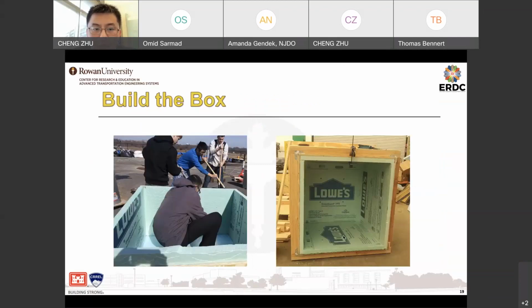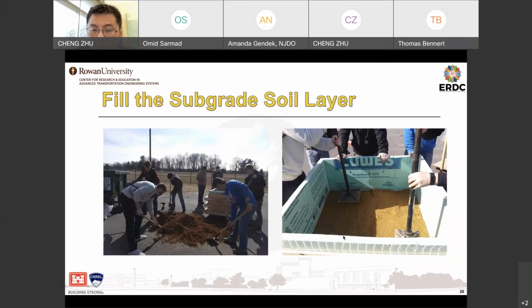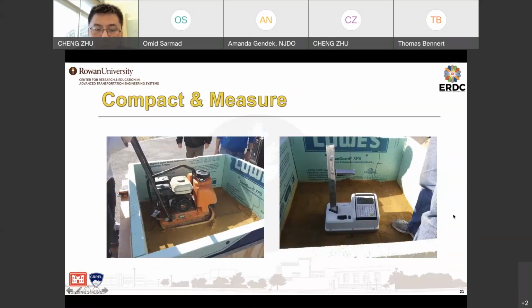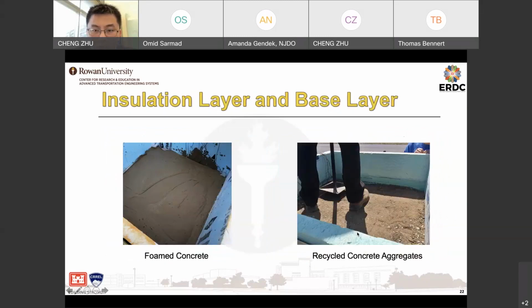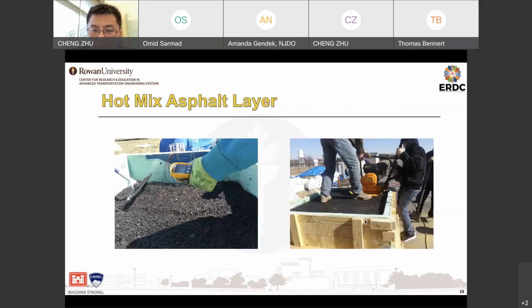Here are some of the pictures we have when we build this soil box. We prepare the soil samples and we compact the soil. This wire is the thermocouple we use to measure the temperature at different depths. And then we compact each layer of soil, and then measure the density for quality control. In the end, this is the foamed concrete we add as an insulation layer. And after that will be the base layer using recycled concrete aggregates. In the end, we put the HMA layer, with all the thermocouples connected to the data logger.